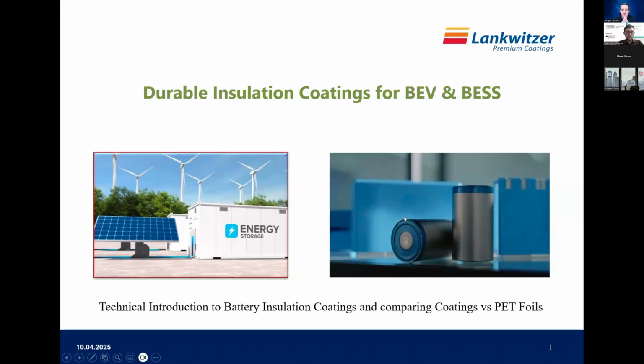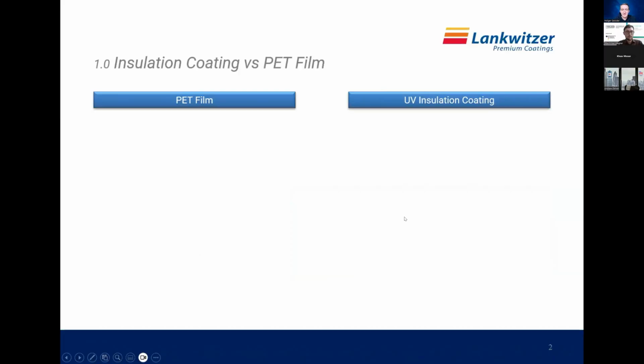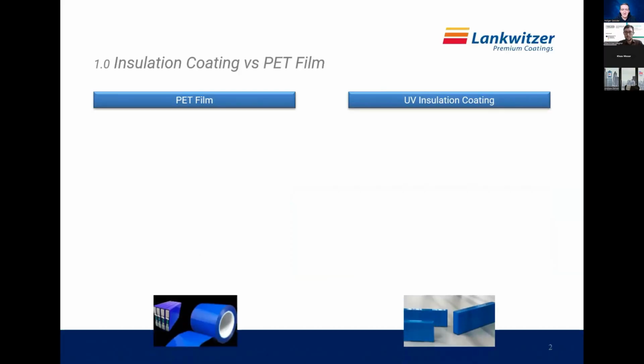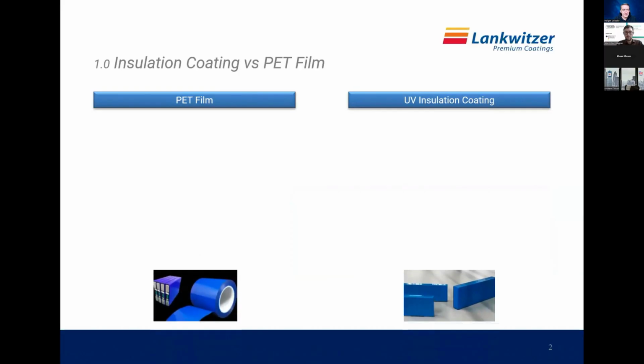What we're going to look at today is basically the difference of durability between PET film, which is used very commonly on battery cells, if they are cylindrical or prismatic cells. The throughput of PET film for the application is 6 parts per minute. Insulation coating, 60 parts per minute. So quite fast.